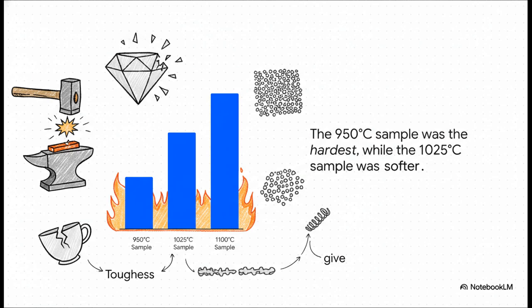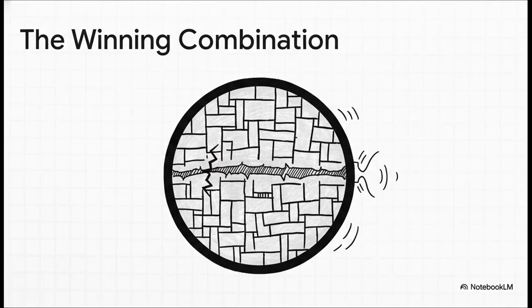And here's a key thing to remember. Hardness and toughness are not the same thing. Something that's really hard can also be really brittle because it has no give. It might resist getting scratched, but it could shatter if you hit it hard enough. So here it is, the winning combination. The 1025-degree sample had grains that were fine enough to make it really hard for a crack to spread. But at the same time, its internal structure was also a little bit softer and less rigid than the 950-degree sample. And that little bit of softness allowed it to deform on a tiny microscopic level, absorbing energy like a shock absorber before it even thought about breaking. It had the perfect balance.